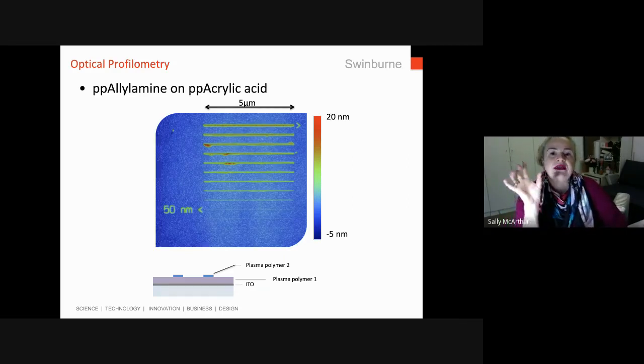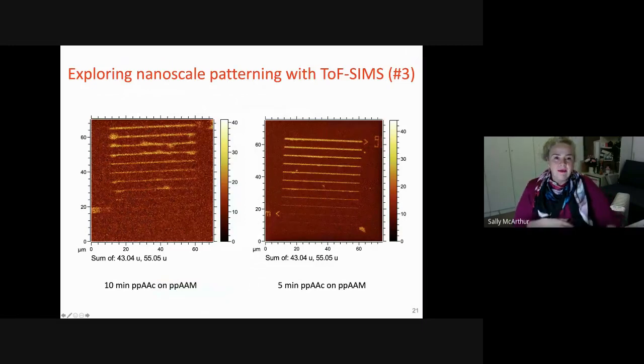And you can see what we've chosen to do is long lines that allow us to locate the feature that we're interested in. And then we're just using a gradient of the sizes of the actual patterns that we're drawing in using the EBL. So that goes from around a 900 nanometer line, or actually I think a 1 micron line, down to, and you can see the line here, it says it's a 50 nanometer line here, and then we go to a 20 and a 10. And this is optical profilometry, looking at the surface, and you can see quite clearly there are differences in the lines, but we actually are interested in the chemistry.